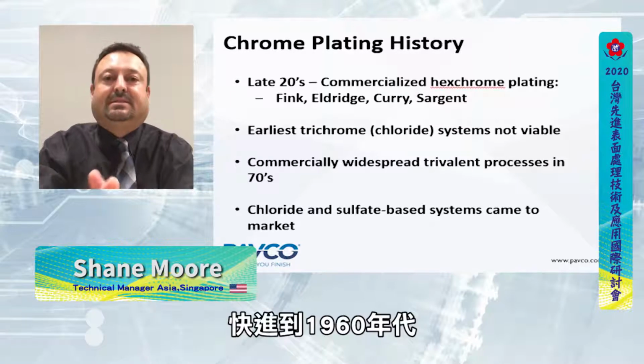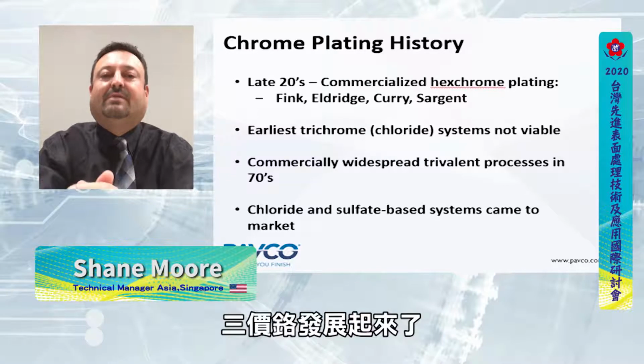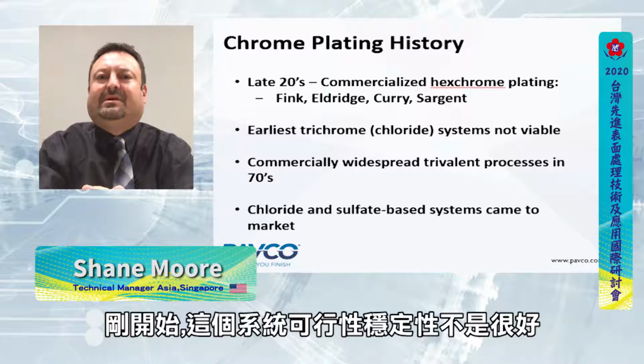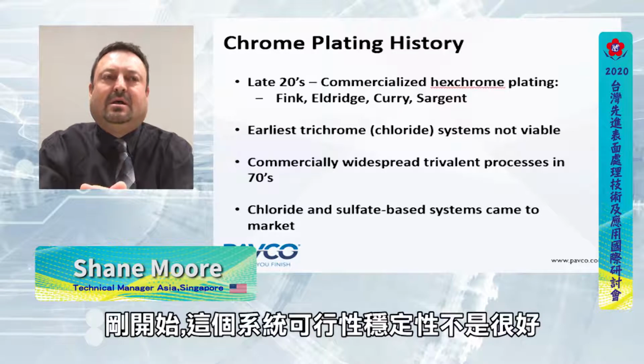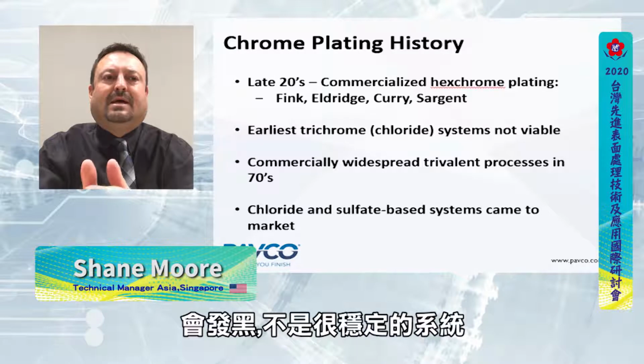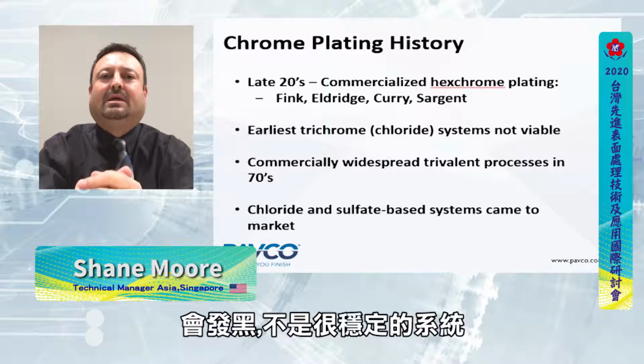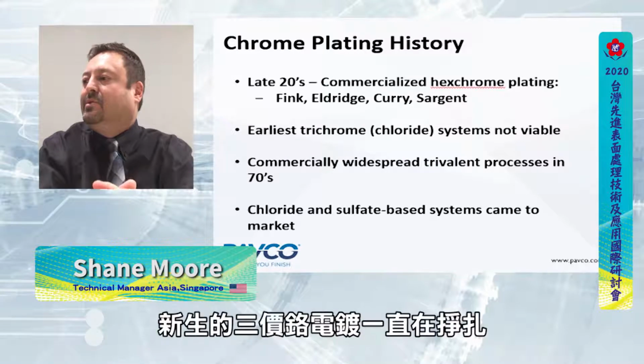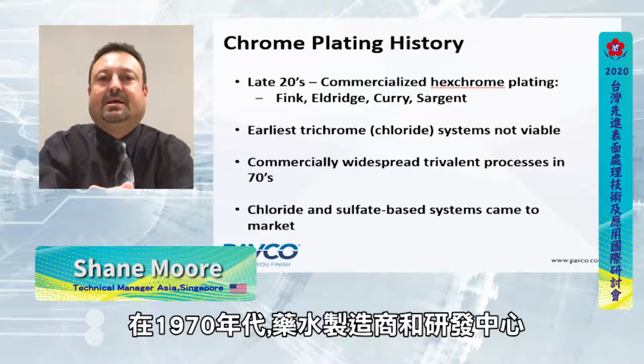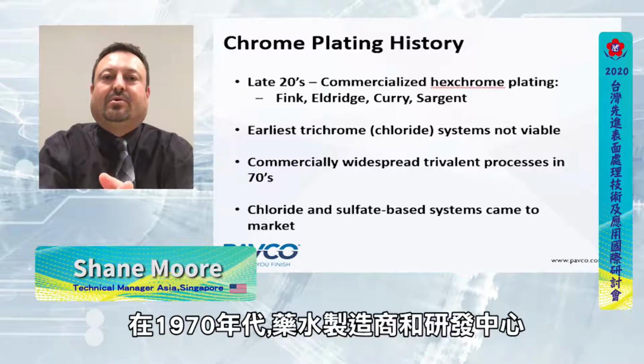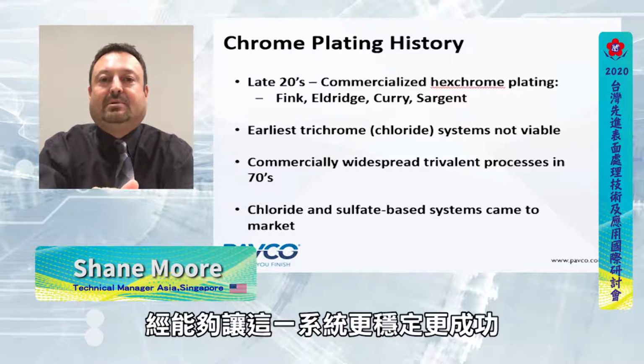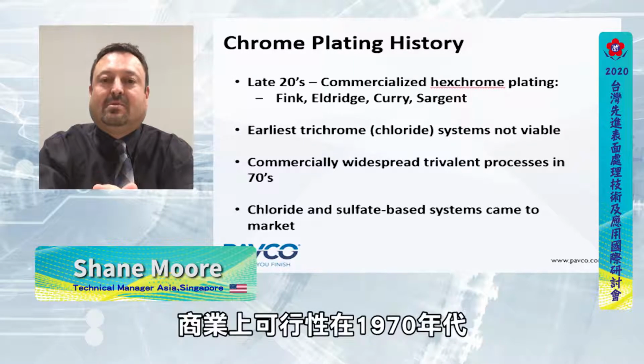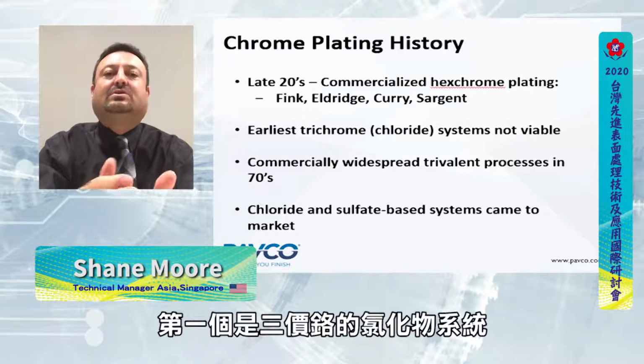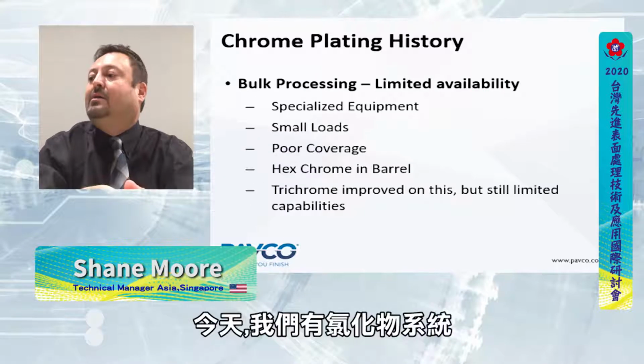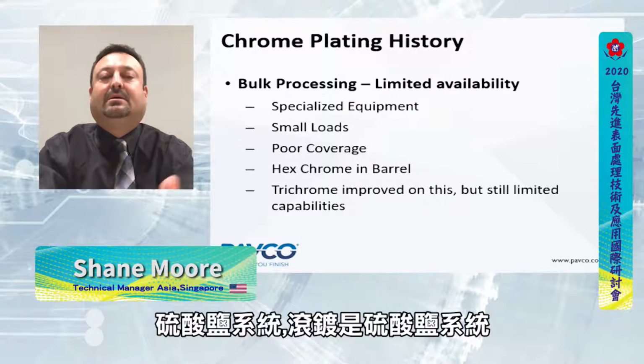Fast forward to the 1960s, trichrome was developed, trivalent chromium was developed. In the beginning, it wasn't a very viable process, it wasn't very stable. It turned dark, and it just wasn't a very stable system. A struggle in the beginning of the birth of trivalent chromium. But then in the 70s, chemical manufacturers and R&D centers were actually able to make it much more stable and were successful, and it was commercially available in the 1970s. The first ones were chloride-based chromium. Today, we have chloride-based, sulfate-based, and the barrel application, which is also sulfate-based.